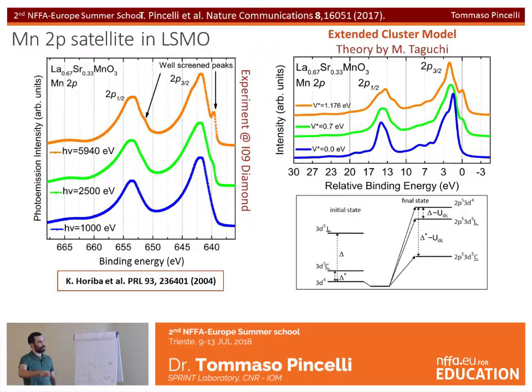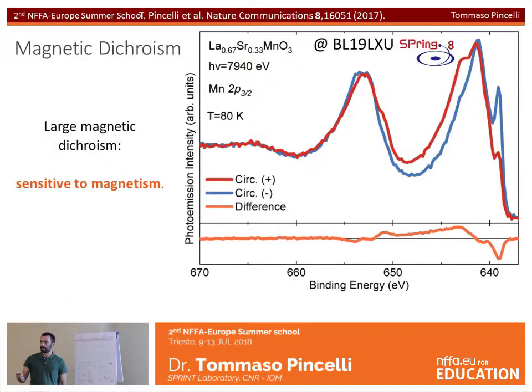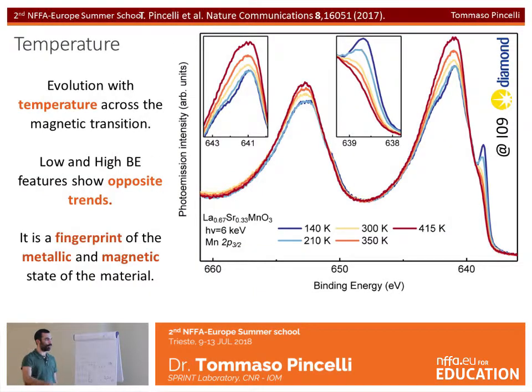This peak also shows a significant contrast when we measure it with circular polarization and opposite magnetization. So by using the selection rules, we can say that it is magnetic. It is sensitive to magnetism too, and also changes shape as we cross the Curie temperature of the material. So we have a confirmation that this is a fingerprint of the metallic and magnetic state of the system.